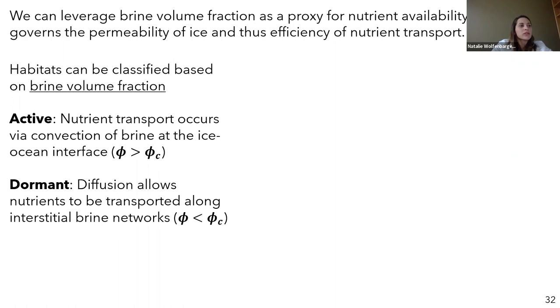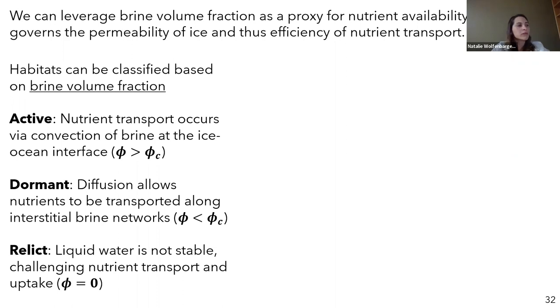Dormant habitats would be those where brine is stable, but fundamentally nutrient transport would have to occur via diffusion along interstitial boundaries, since convection is not possible at that percolation threshold. And then finally, relict habitats, essentially where liquid water is not stable, which will challenge the nutrient transport and uptake, but some works have argued not to necessarily prevent it. But in our work, we're going to just adopt this classification.